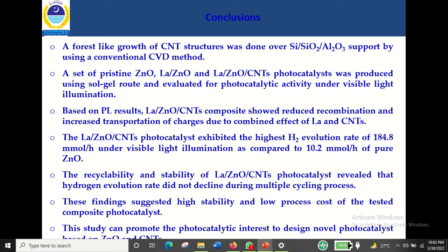The results show that the composite photocatalyst in the presence of carbon nanotubes shows reduced recombination and increased transportation of charge carriers due to the combined effect of lanthanum and carbon nanotubes. The composite photocatalyst exhibited the highest hydrogen evolution rate of 184.8 millimole per hour under visible light illumination, as compared to 10.2 millimole per hour by the pure ZnO.